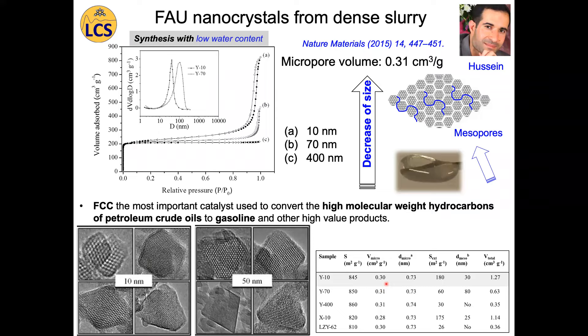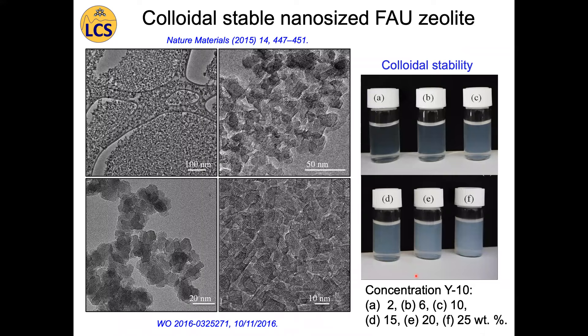These ultra-stable nanosize faujasite crystals were stabilized in colloidal suspensions with concentrations varying from 2 to 25 weight percent and stored at ambient conditions for several years. These nanoparticles do not sediment and do not change with time — they remain very stable colloidal suspensions. We are interested in these stable suspensions because we would like to use them as coating materials or as injectable nanoparticles for biomedical purposes.